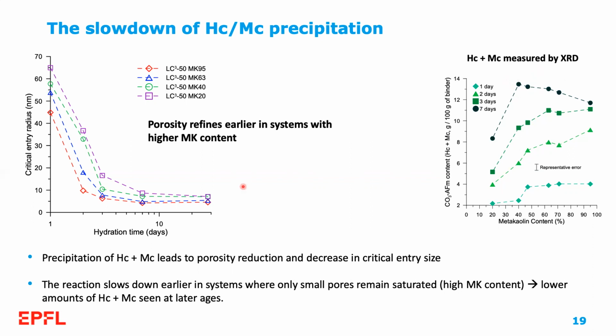The reason for this is that the precipitation of hemi and monocarboaluminate leads to a porosity reduction and a decrease in the critical entry size in the porosity of our material, as we see here in the plot. And this refinement occurs earlier in systems with higher metakaolin content. We can see here that 95% becomes refined as early as 2 or 3 days, while the system with 20% metakaolin takes about 7 days to reach the same degree of refinement. The reaction then slows down earlier in systems where only small pores remain saturated, in this case in systems with higher metakaolin content. And this is why we observe lower amounts of carboaluminates at later ages.